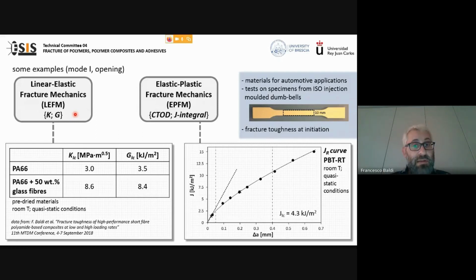Instead, here in the box on the right, I have reported a J-R curve, that is a resistance curve, in which the values of J are plotted as a function of the crack advancement delta a. A value of J at fracture initiation was determined, and this curve refers to a rubber toughened polybutylene terephthalate. Both this rubber toughened PBT and this compound were developed for automotive applications. Of course, also in this case, let me underline that we could successfully apply a protocol, a method developed within the elastic plastic fracture mechanics.